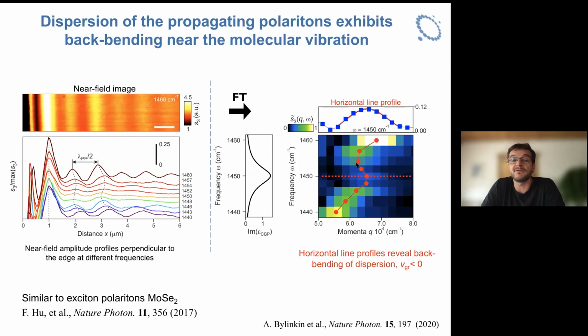We see the momentum decreases, which corresponds actually to the increase of the wavelengths. So this anomalous dispersion is induced due to the coupling between the molecules and the phonon polariton. This negative slope corresponds to a negative group velocity actually. This is not a big deal. So a pulse would propagate backward, which does not mean that the energy propagates backward. That is just a reshaping of the pulse shape due to this negative group velocity induced by these molecules.